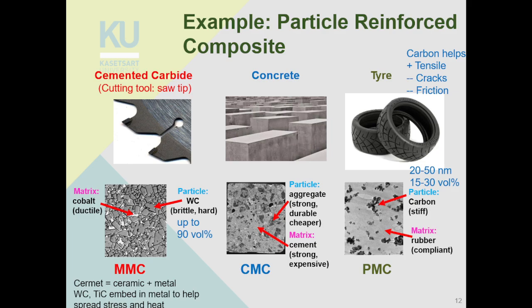Okay, example of particle reinforced composite. Okay, the first one is the cemented carbide, cutting tools, saw tips, etc. So if you look closely at the tip of the cutting tool, it's not just pure metal. If you look closely under a microscope, you can see it is actually a metal matrix composite, with particles. In this case, it is tungsten carbide particles that are glued together by cobalt, which is a metal matrix. Right? Tungsten carbide is really, really hard, but it is also brittle. Okay, so we cannot use tungsten carbide to form the tip alone because it is very brittle. So when you cut something, the tip will hit on that material and it will break.